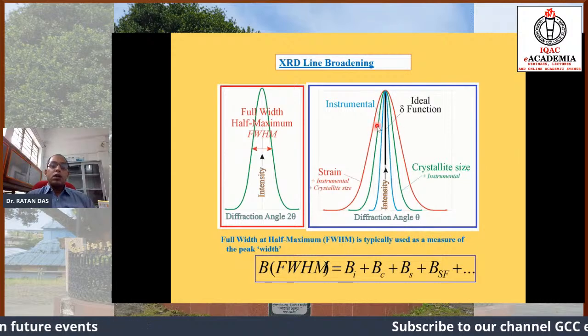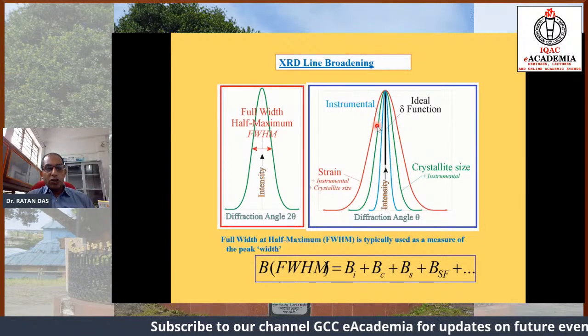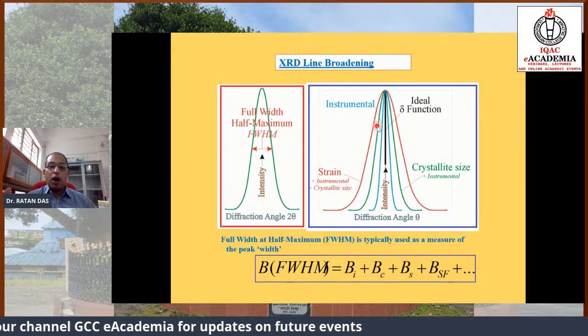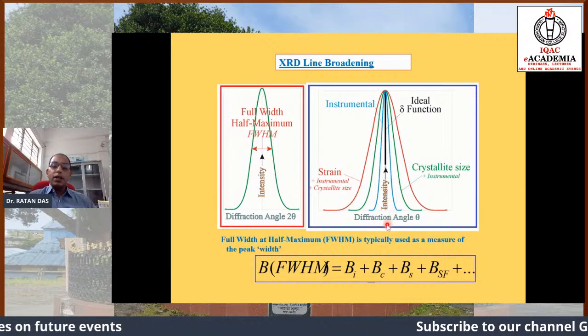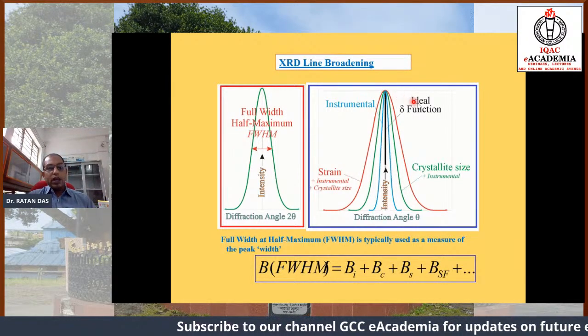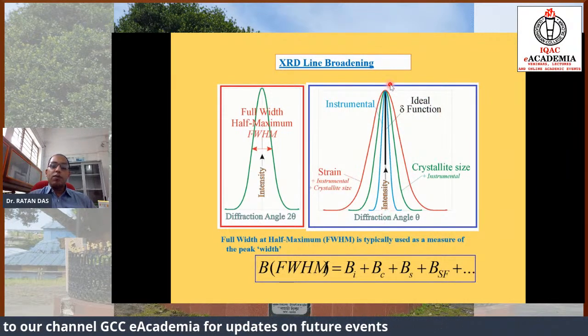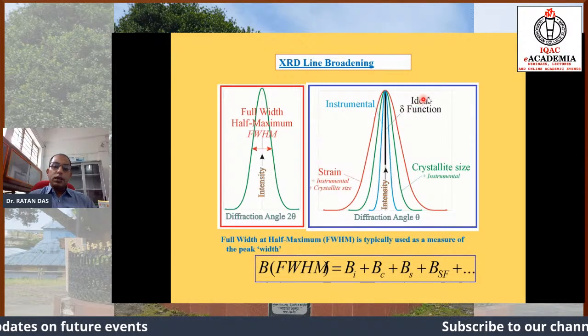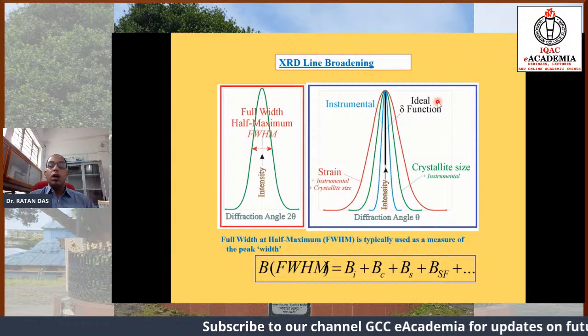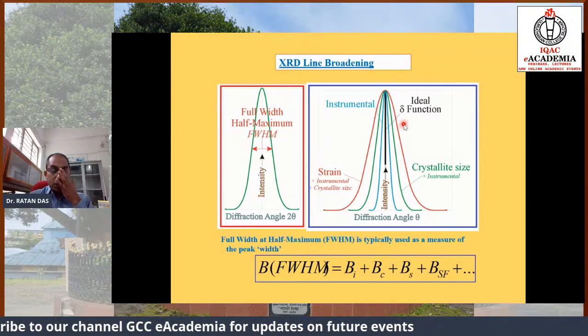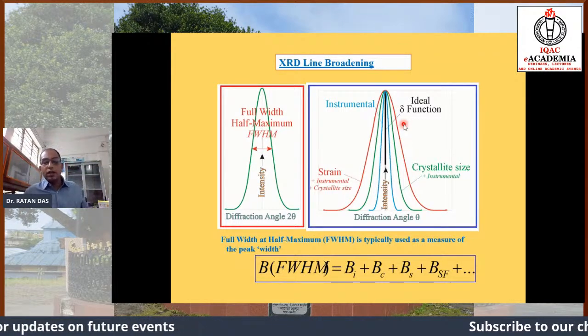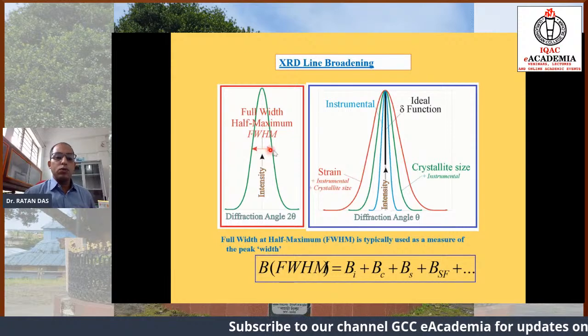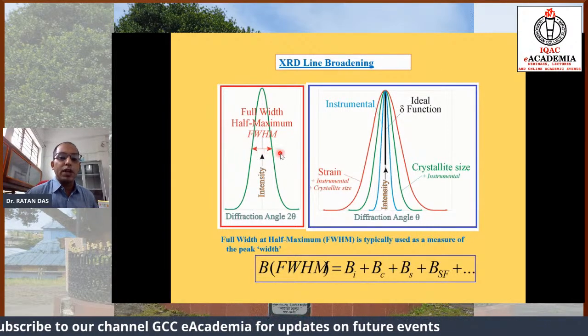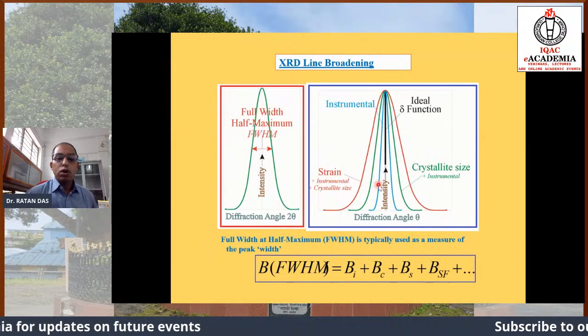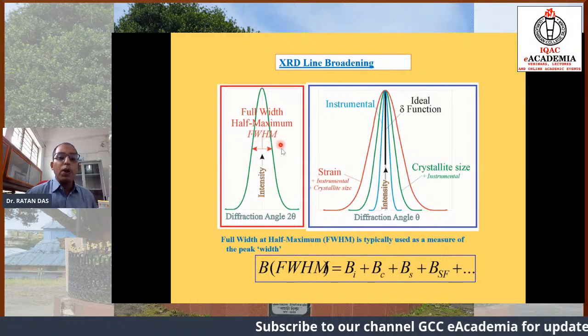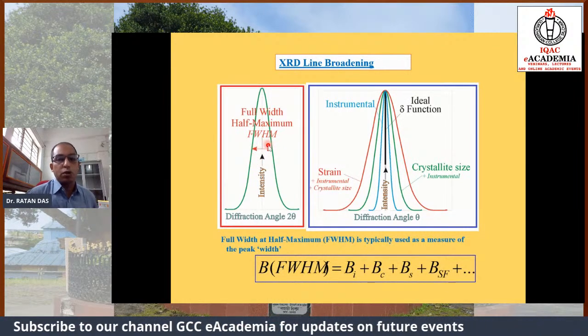Another thing that I want to say is that if we study the X-ray diffraction pattern of an ideal bulk material of infinite size, we obtain a diffraction pattern which is infinitely peaked. Rather, I can say it is the ideal delta function. A delta function is infinitely peaked with no width actually. And this is the ideal diffraction pattern that we obtain in the case of a big bulk sample. But if we go to smaller sizes in the nano range, you will observe a width in the X-ray diffraction pattern. So what I want to say is that size plays a role in the broadening of a diffraction pattern.